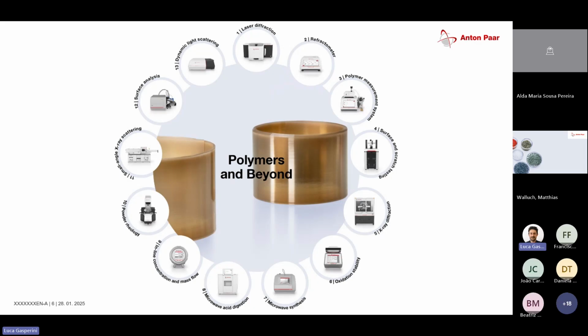Then down here we get super special. We also have surface and scratch testing. There are smaller versions of this for nano-indentation testing, to get an idea of how homogeneous the surface is. If you're working with paints or coatings and you want to understand how the coating sticks to the substrate, you can do a scratch test. You just indent, then pull the sample and increase the pressure, and you get an idea there as well. Then we also have XRD, if you're interested in crystallization hierarchies, for example.